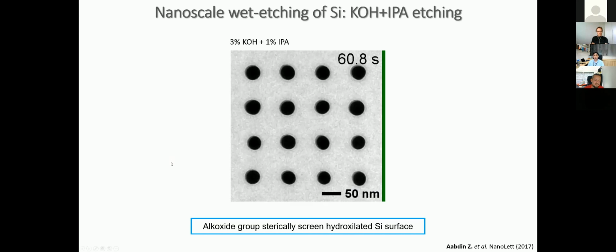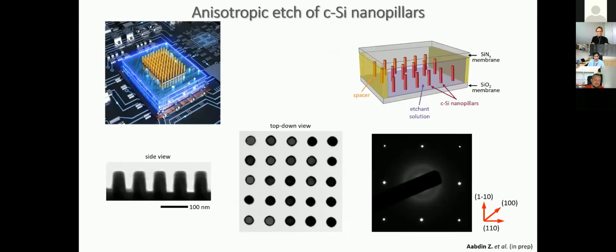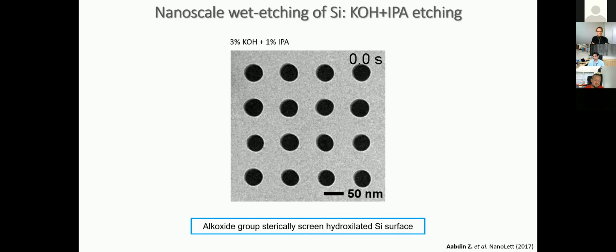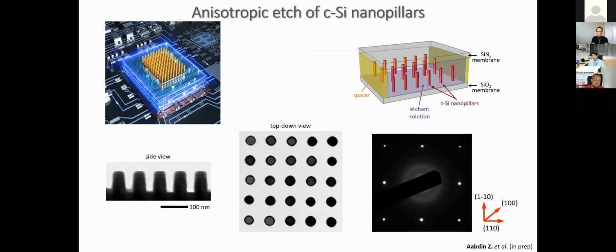So here what I show you, this is amorphous silicon. The same thing can be done for the crystalline, right? So the reason we did this amorphous here earlier is because there is no way you can grow a crystal on top of a nitride. So we really had to kind of change our design of our holder. So we had to do this on a SOI wafer.